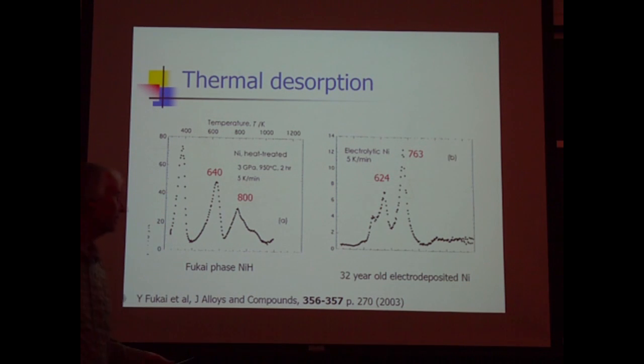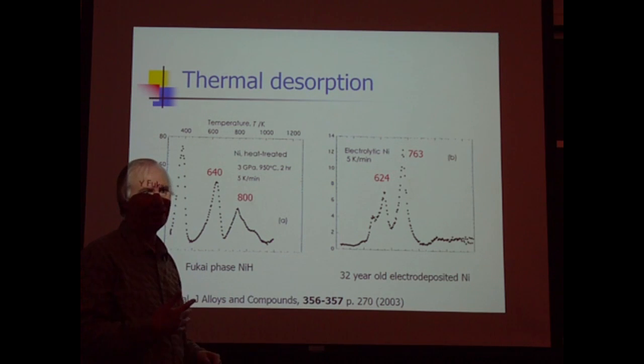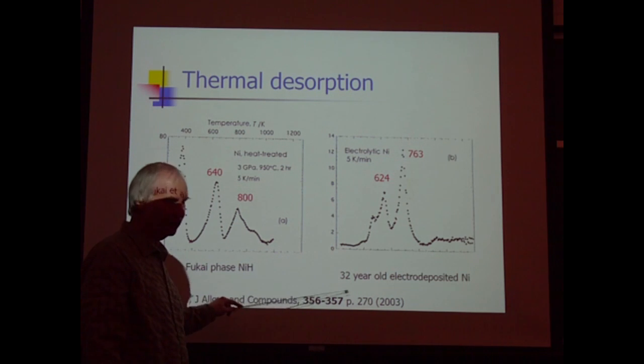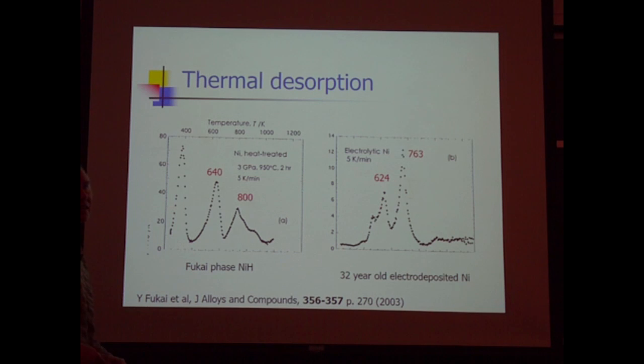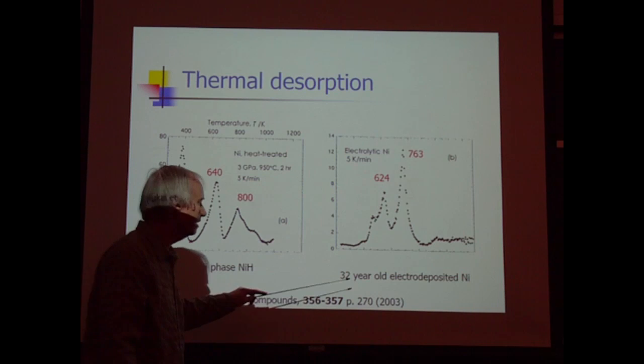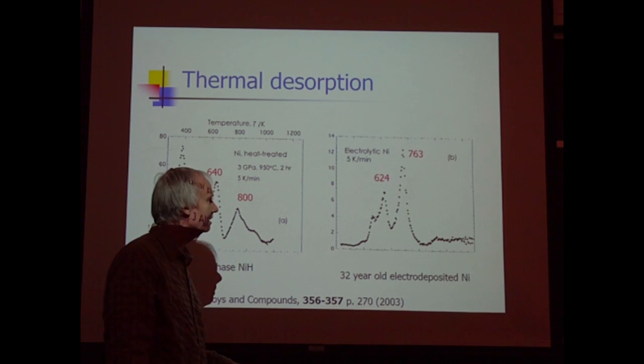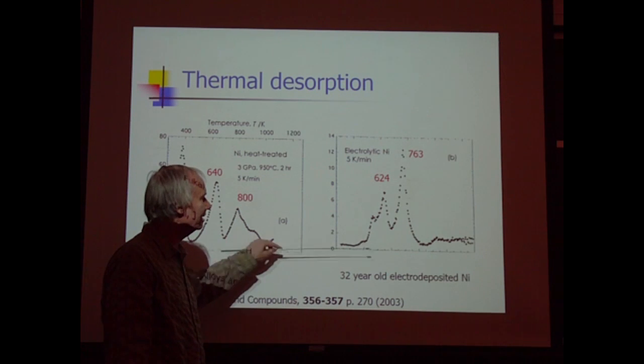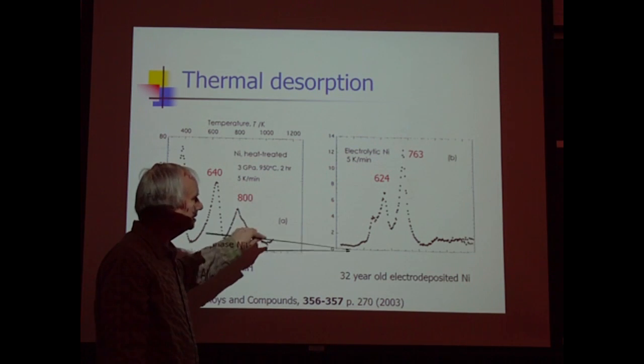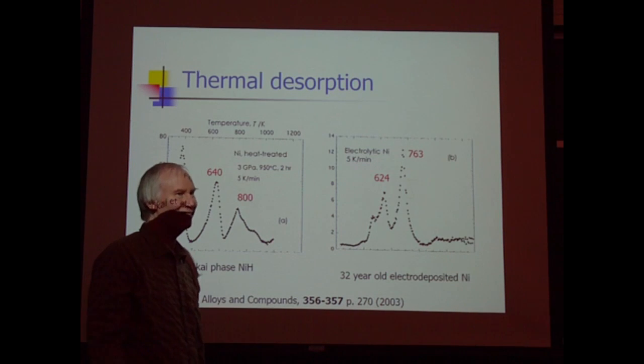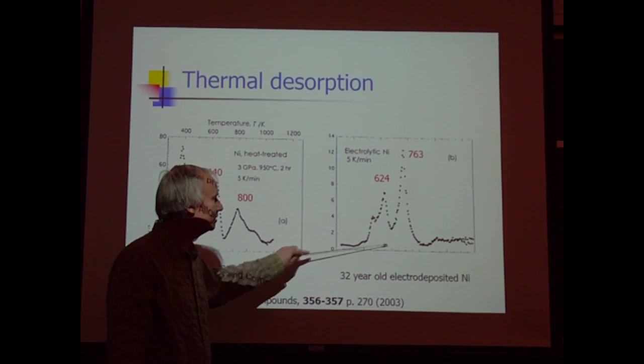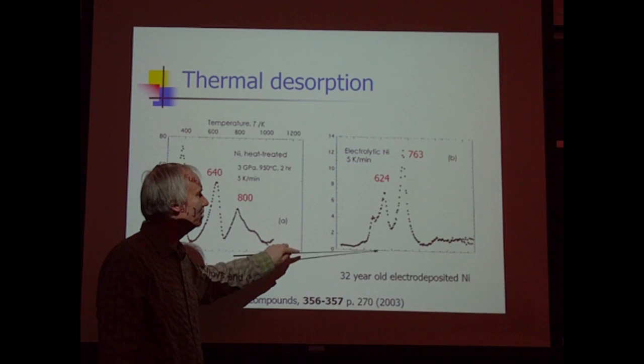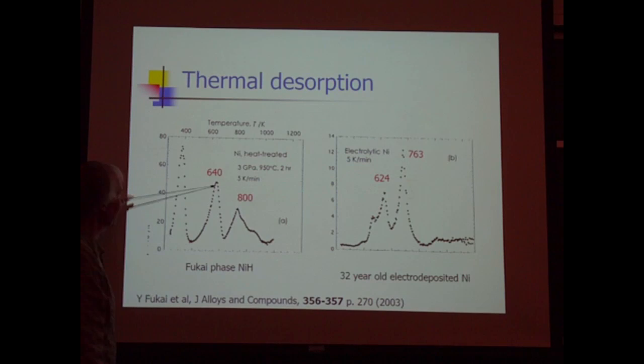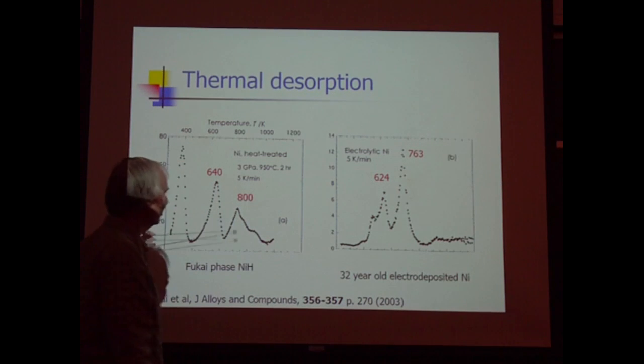So then, at issue is: can you make vacancies in electrodeposited nickel? Fukai was interested in the issue of stability of the vacancies. If you make Fukai phase material, you make these vacancies. Do they stick around? So he got 32-year-old electrodeposited nickel and did a thermal desorption scan on it. There's no 400 K signal, basically, because it's been sitting around and all the hydrogen is gone. But the traps can retain some hydrogen, and when he heated them up, he saw emission at 624, which is sort of like the 640, and he saw 763, which is like 800.